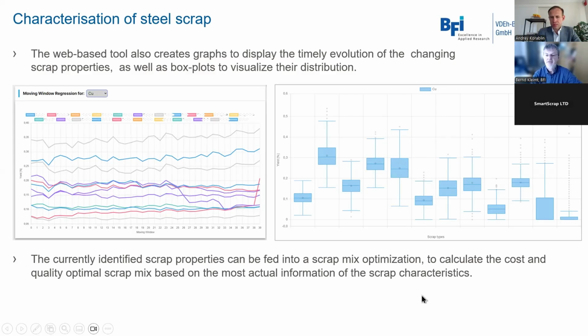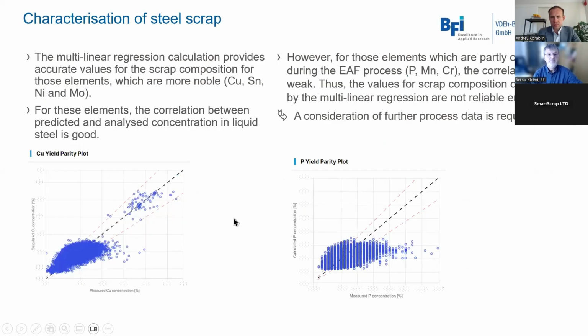And also, we use these scatter plots, the box plots, to see how the properties of the different scrap types scatter regarding the different element composition, for example. So what we found in our investigations is that this multilinear regression calculation provides accurate values for those elements which are more noble than iron, for example, copper, tin, nickel, and molybdenum. So for these elements, the correlation between predicted and analyzed concentration in liquid steel is very good. But for those elements which are reacting with oxygen, like phosphorus, manganese, and chromium, this correlation is much weaker.